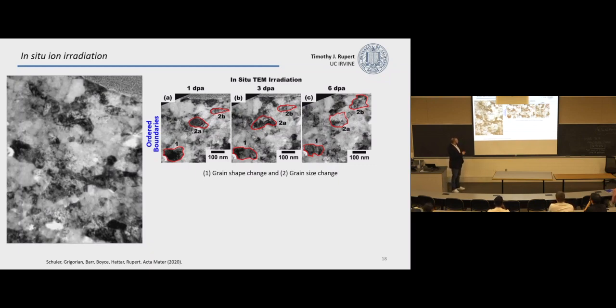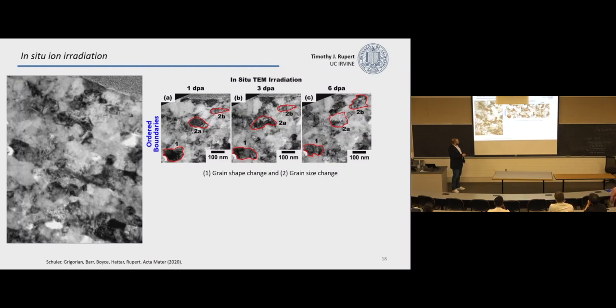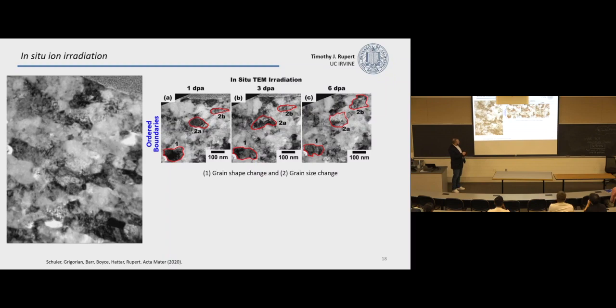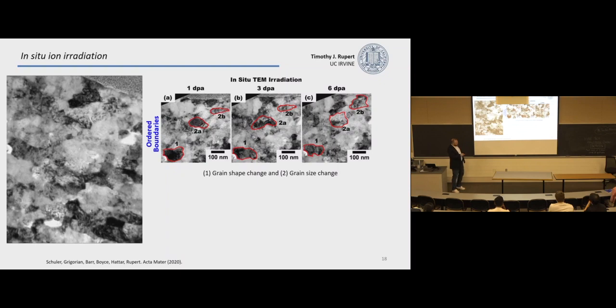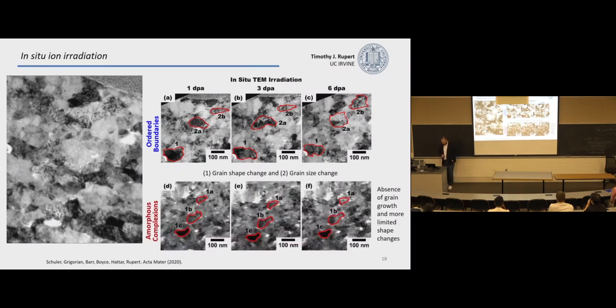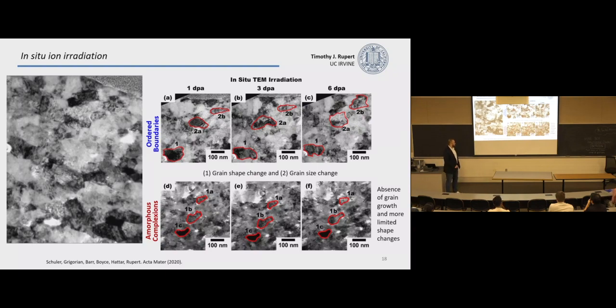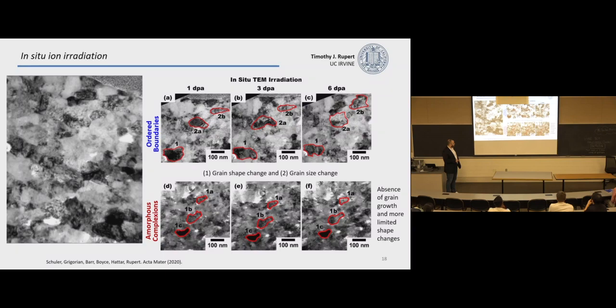For the samples with ordered boundaries, we see both changes in grain shape, but also changes in grain size. So this is an example where you see some modest changes in the shape, but here you see this grain has grown quite a bit after we damage it a little bit. And even just on the surface, if you look at the amorphous complexion examples, we see the absence of grain growth. We only see changes in the grain shape. So the microstructure is more stable.